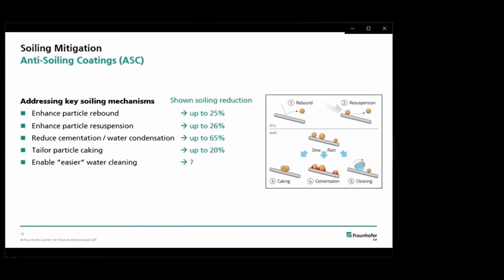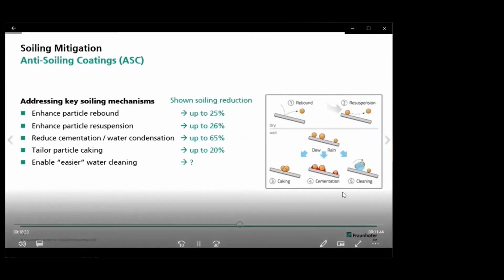And there are different mechanisms which we found to be important, which could reduce soiling, including the effect of rebound, when particles bounce directly off the surface during impact, and also the effect of resuspension when wind blows off the particles from the surface. In addition, there have been also some studies on the interaction with dew and rain, and there we detected the processes of caking, which is kind of particle agglomeration at the surface, which could reduce the optical losses, as well as cementation, which fixes the particles at the surface and permanently glues them together with the glass. And last but not least, also the self cleaning, for example, during rain.